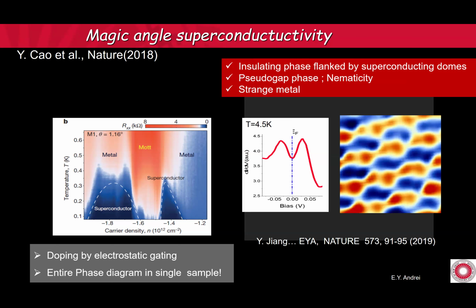How did you know that was nematic, just out of curiosity? Okay, this is +1 electron per Moire. This is -1 electron per Moire. And what we did is you move your Fermi level. The way you know that, if you just integrate over the density of states, the dI/dV curve. So let's say that my Fermi level is here. I integrate from here to here, I know the filling, and then I integrate from here, I know the bandwidth, so I know what the filling is, and you do that at every point. And you end up with the line here being 1 electron per Moire, and this is one hole.